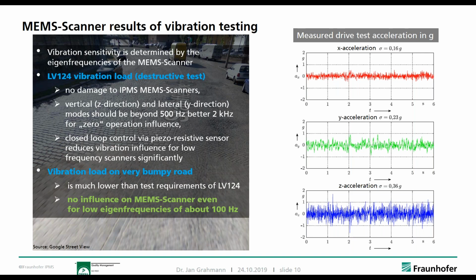So compared to what we actually saw on the road, where the test requirements are, the vibration load is much lower than we actually expected. It shows that there's no influence even on the softer scanners around 100 Hertz at all, because the acceleration levels are much lower than our used destructive test.